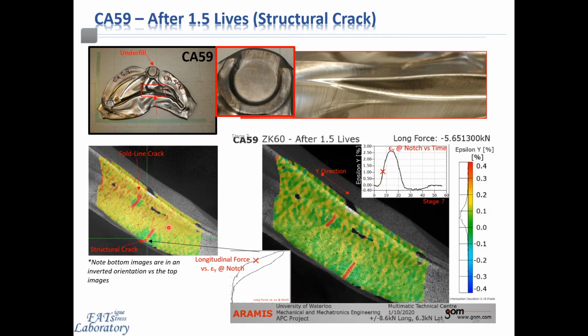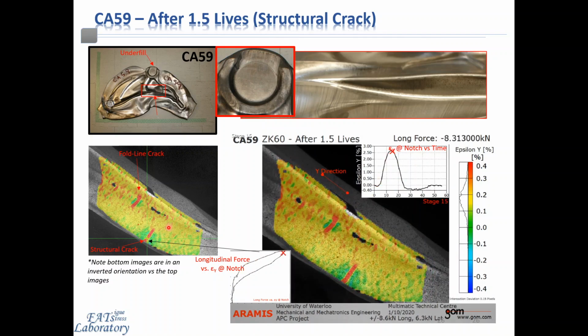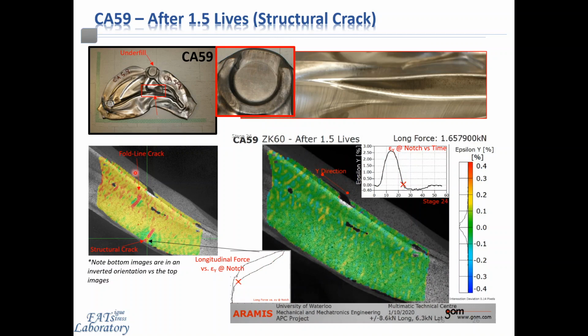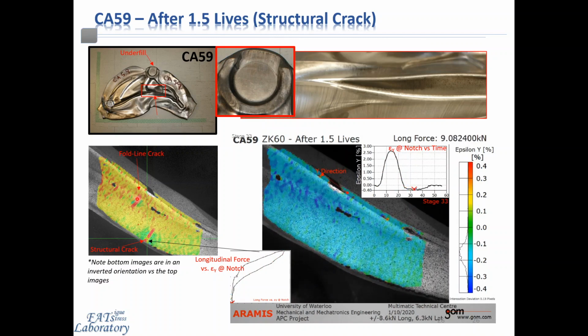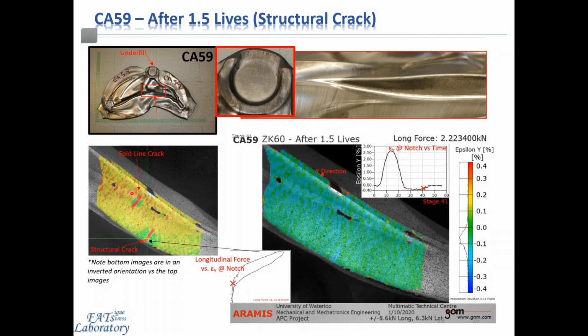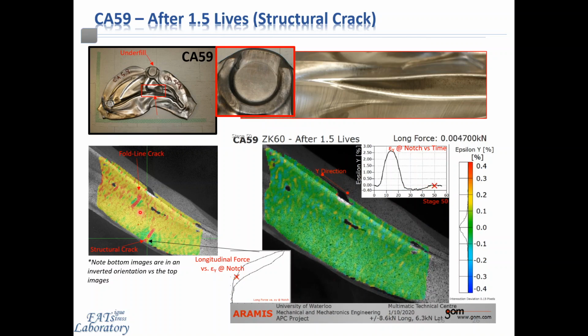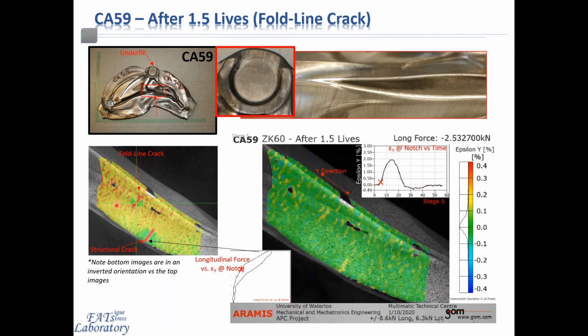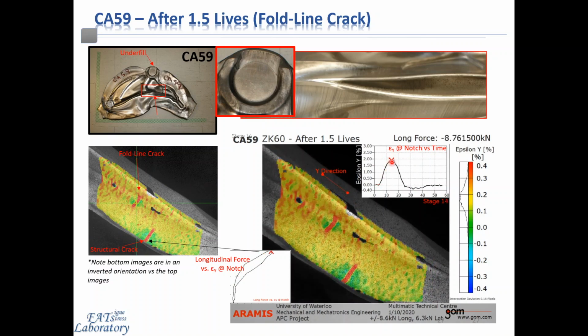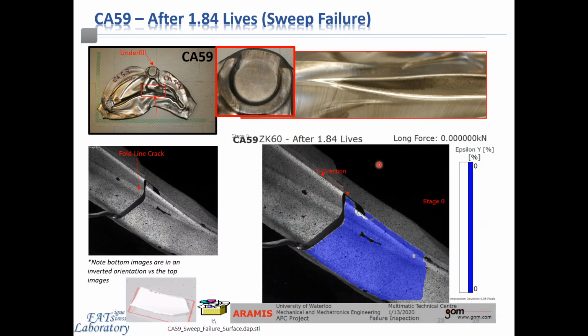However, when we go to 150% of the fatigue life, we can observe that now there are two cracks, the second of which nucleated at a location which was similar to the previous component. Which one will propagate first to eventually cause the failure of the component is an excellent question that one might ask themselves at this stage. Here we can see that the peak strain at the location of the first crack here is 2.5%. However, if we look at the peak strain in this other location, it's slightly less, around 2%.